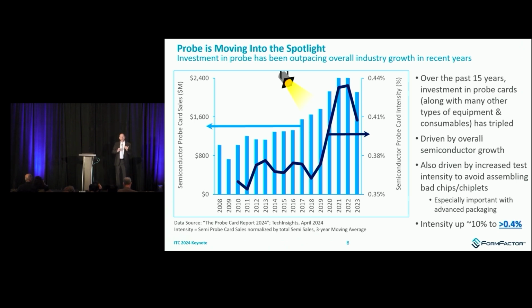Probe card spending, or intensity normalized by semiconductor revenues, has gone up by about 10% starting in the 2018-2019 timeframe. That's for the reasons we talked about in the first slide. One, the desire and capability to shift test content left to wafer probe. Two, the onset of advanced packaging and the beginning of the adoption of chiplet and 3D packaging strategies that, as you'll see in a second, almost require known good die to be economically viable.